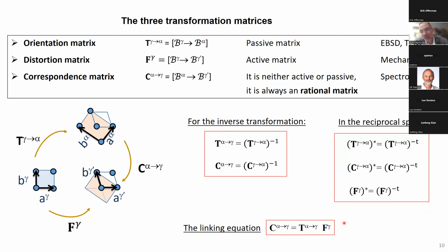Okay, since we will do crystallography, I need to introduce here 3 types of transformation matrices. First of all, I need to define what is an orientation matrix. I told you that in martensitic transformation we have an orientation relationship. So we can encode this orientation relationship by a matrix in which we have the daughter phase here, the martensite. In this example, it's a rectangular centered phase. And we have the parent phase here, that is simply a square.